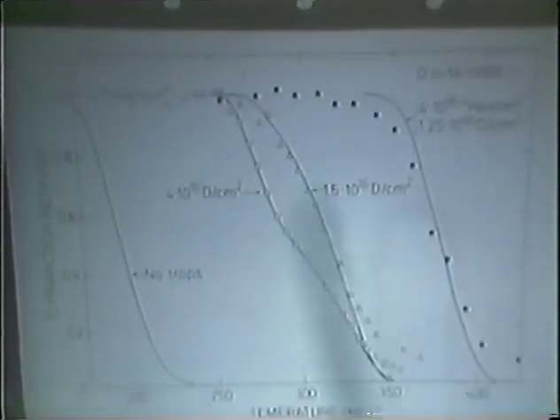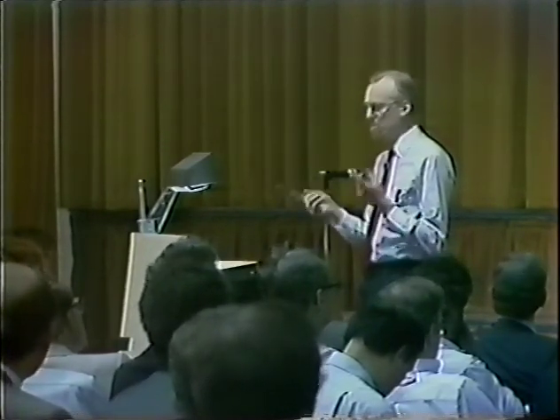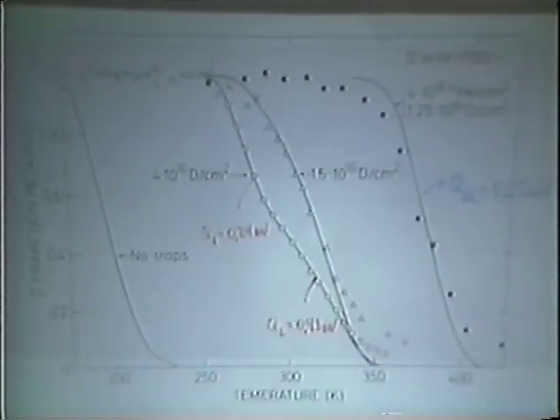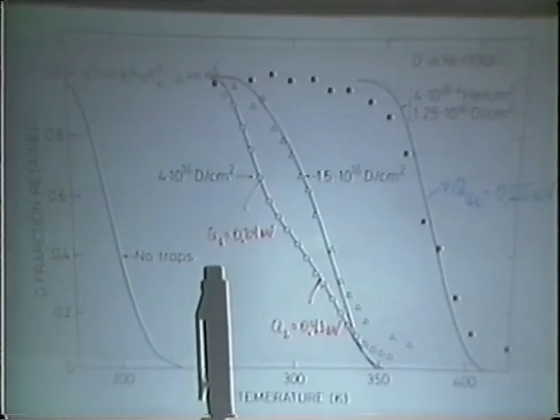The way we extract binding energies here is that we model all these release curves by a diffusion calculation, which takes proper account of trapping and retrapping from the traps. We include the known hydrogen diffusivity, we include the vacancy and the interstitial mobilities, and we include vacancy and interstitial annihilation, and also the multiple occupancy of the traps. We then get trap strengths, which are listed here for nickel: 0.55 eV for the bubble traps, 0.43 eV for the vacancy trap, and 0.24 eV for the multiple occupancy if you have more than 2 hydrogen in a vacancy, all with reference to a solution site in the lattice.